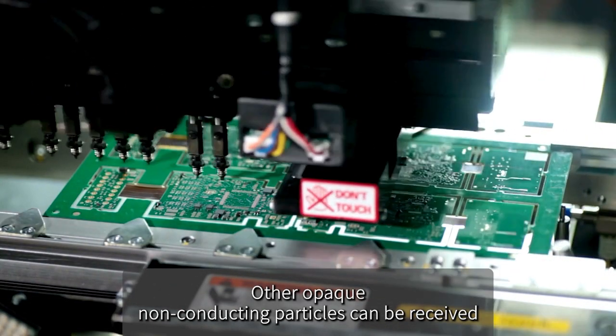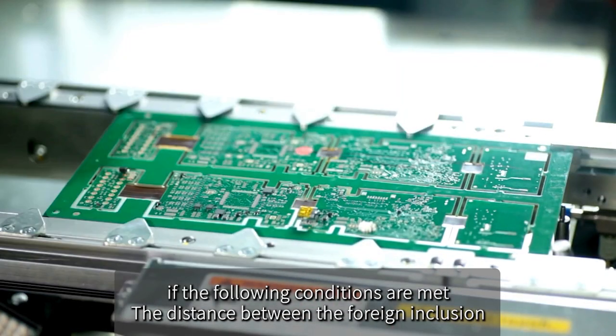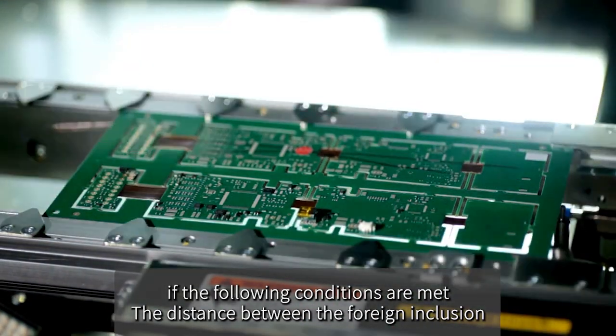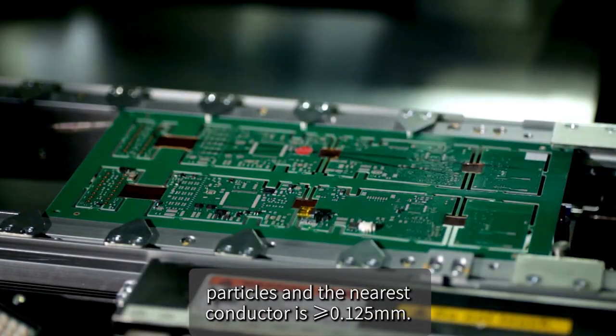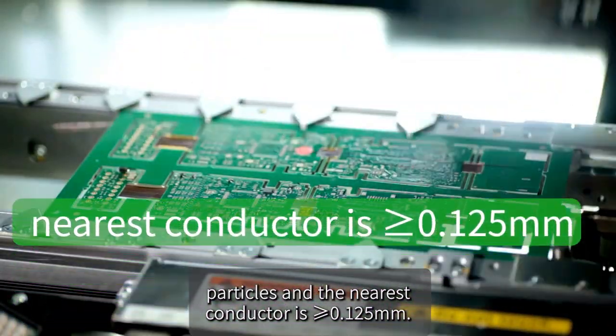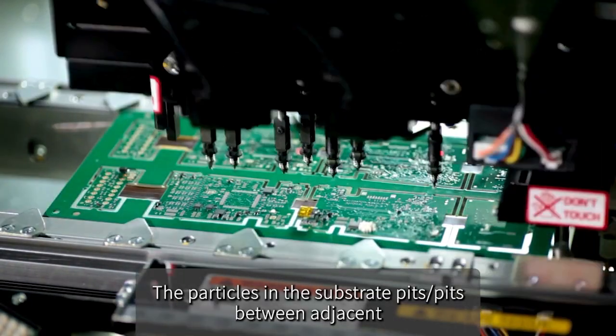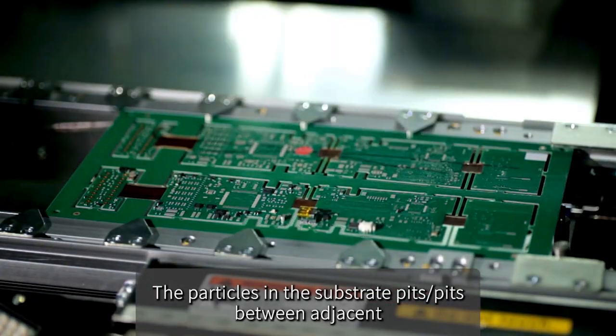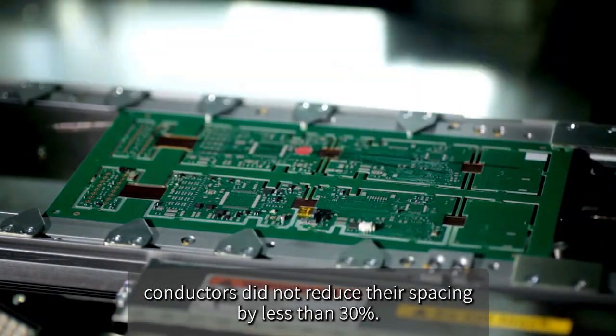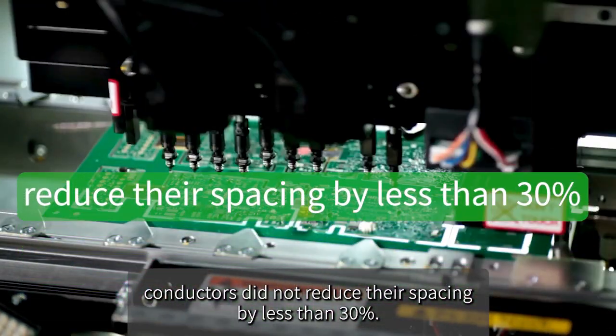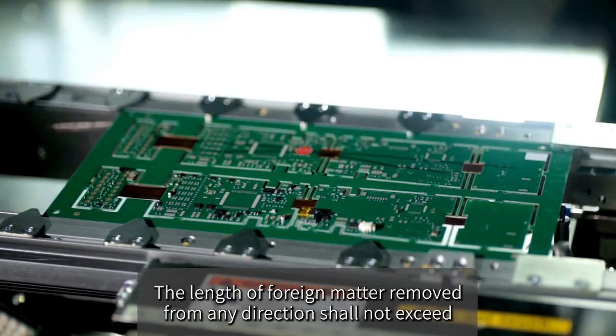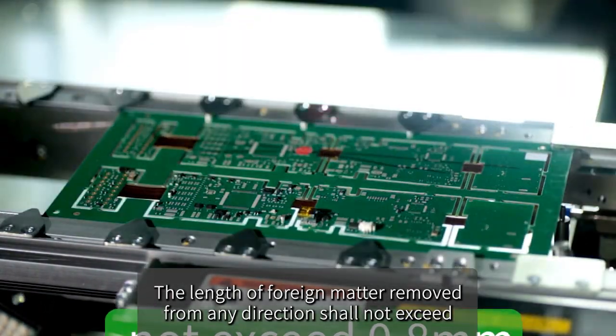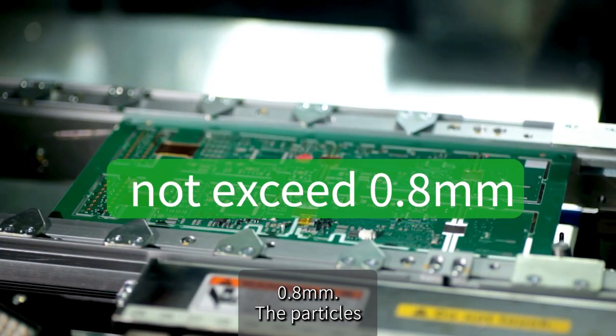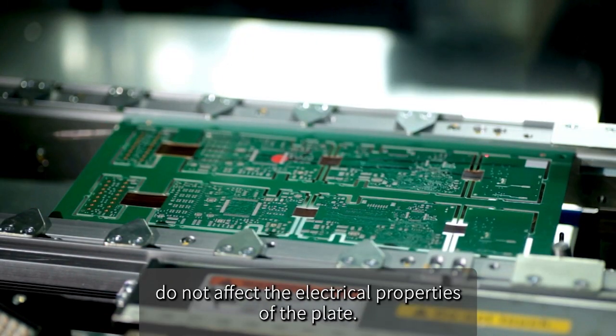Other opaque non-conducting particles can be accepted if the following conditions are met. The distance between the foreign inclusion particles and the nearest conductor is greater than or equal to 0.125 mm. The particles in the substrate pits/pits between adjacent conductors did not reduce their spacing by more than 30%. The length of foreign matter removed from any direction shall not exceed 0.8 mm. The particles do not affect the electrical properties of the plate.